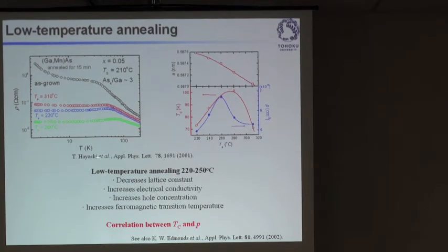And the University of Tokyo group first noticed that you can actually reduce the resistance or increase the conductance of the material, and at the same time you increase the transition temperature. So there's something going on in the material after growth. And people haven't done this before because many people believed that annealing at the same temperature as the growth temperature doesn't do anything to the material, but it wasn't correct.